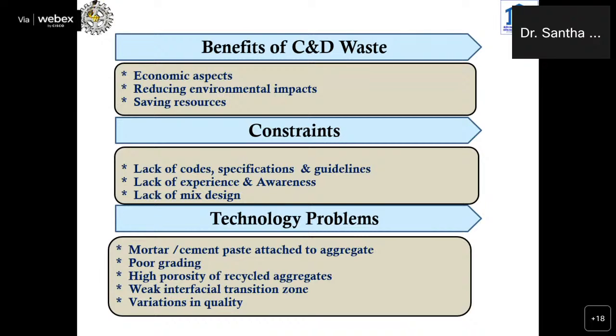The first issue is the mortar or cement paste attached to the aggregate. Second is poor grading. Third is the high porosity of the recycled aggregates. Fourth is the weak interfacial transition zone. Whenever we prepare recycled aggregate concrete, it usually has two ITZs. As we all know, one ITZ is between the new cement paste and the old cement paste. That is the weakest zone, the weakest link for both mechanical and durability performance. The other ITZ is between the old cement paste and the natural aggregates.